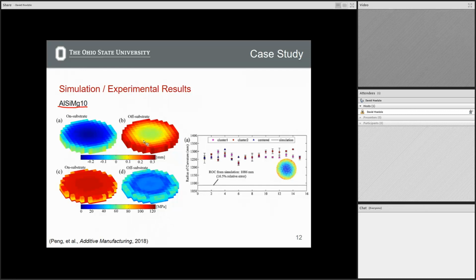And now it blows up. So when it's on the substrate, pretty flat, very minimal distortion, you have the ability to relieve this residual stress via post-process heat treatments, which we'll talk about later in this module. But that is an extra expense in your manufacturing process. And so you may not want to do that, but if you remove this, you get a pretty large distortion. So you get somewhere on the order of 0.3 millimeters.